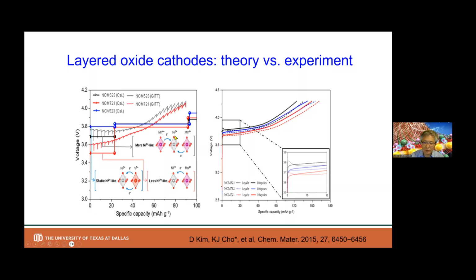And on the right-hand side, what we are showing is that as we go through the cycle life, the cathode materials go through slight capacity degradation, which is the main part of the discussion: why capacity is changing, what is going on, and how we address this capacity change problem in lithium-ion battery cathode material. This experiment shows these changes, and the theoretical analysis shows the level of confidence that we can predict and understand the material behavior and its change with reasonable accuracy, at the level of less than 0.1 volt.